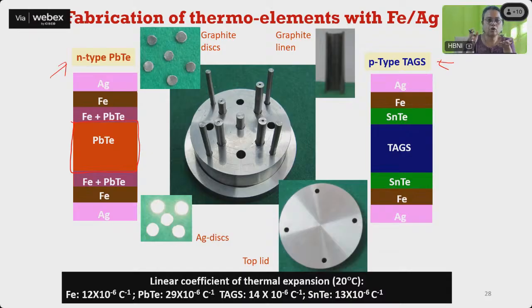But because we have to now electrically and thermally couple them, how to couple them? We cannot just put silver pads directly. We have to match the thermal expansion coefficient, because if you are making it into a device and the thermal expansion coefficient of this material and, say, silver does not match... So if you see here the linear thermal expansion coefficient for iron is 12 into 10 to the power minus 6. Lead telluride is 29 into 10 to the power minus 6. Sorry, TAGS is 14 and tin telluride is 13. So we are matching it.